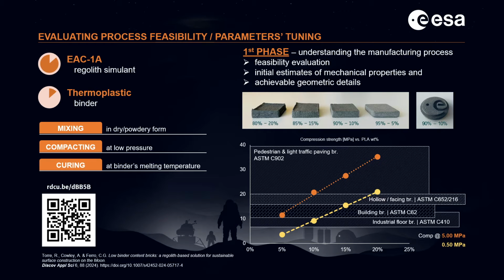Our process is considering at the moment EAC-1A, which is the regolith simulant we use at European Astronaut Center, and PEEK as the thermoplastic binder. Actually, you will see in this first slide that at the beginning we were also using PLA or polyethylene. The idea was simply to understand the process a little bit more, and then to switch to the real polymer we wanted to use. So the process is really simple.